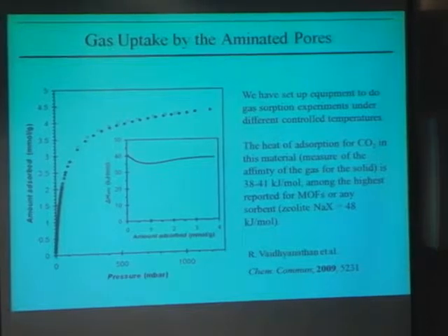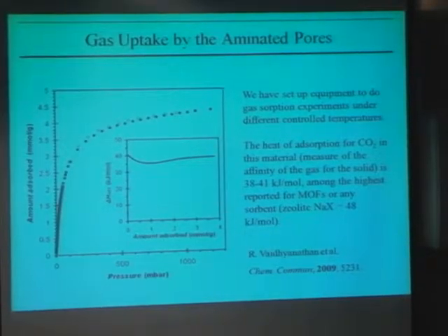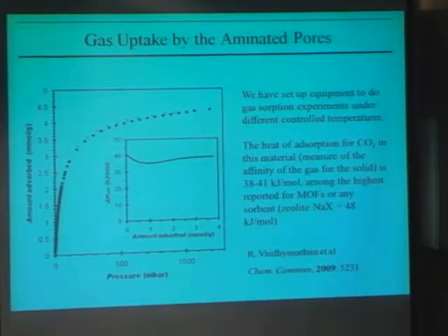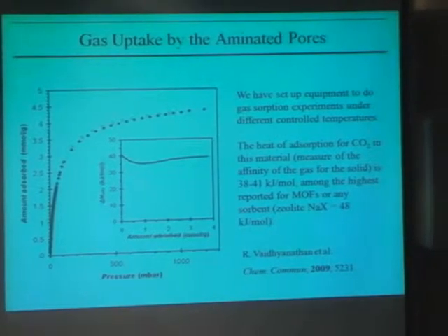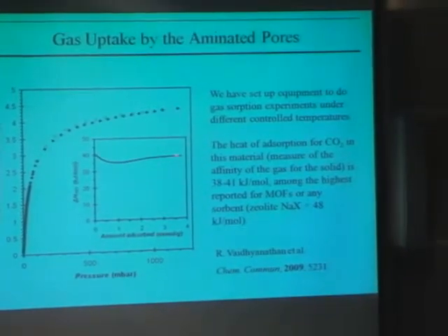Doing this experiment at a few temperatures, you can get a plot of delta H adsorption. So this is heat of adsorption, just a measure of the affinity. Something that was really interesting here was this curve. A lot of papers will plot this and it just drops down like that. Essentially with coverage, as I was saying, you'd want one layer to polarize the next layer, but that effect just gets insulated the further out you go. So typically with coverage, you expect that to drop down. In our case, it dropped down a little bit and then it went back up.